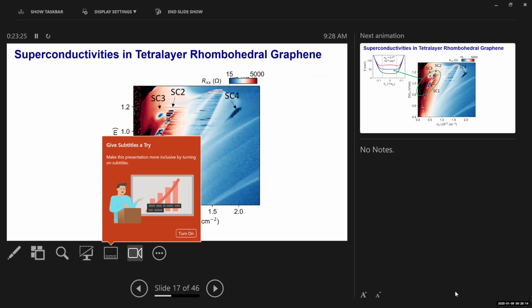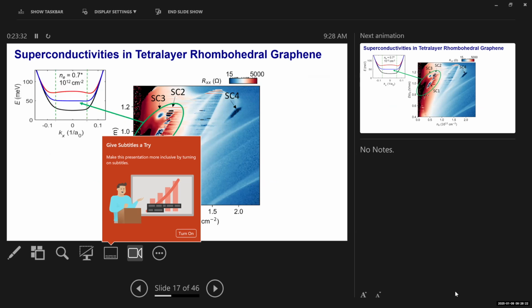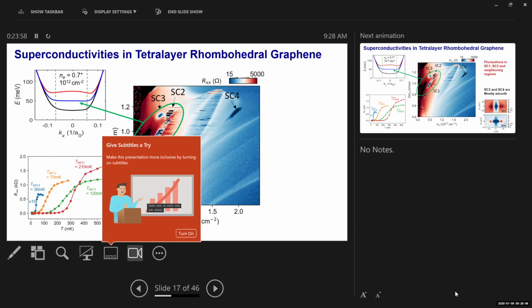You make a Hall device, you vary the charge density, you vary the gate displacement field, and you're looking at one quadrant of this phase diagram that corresponds to when you open up the band gap and dope electrons to the bottom of this very flat conduction band, where the correlation effect is supposed to completely dominate. And you find in the phase diagram there are 4 regions that show vanishing resistance, SC1, 2, 3, 4. And the TC of these superconductors are not high at all.